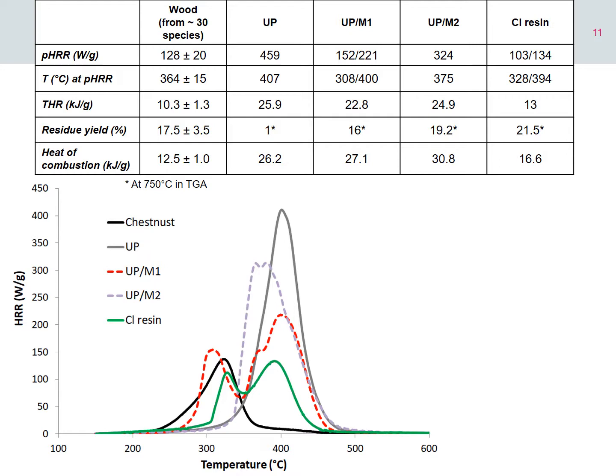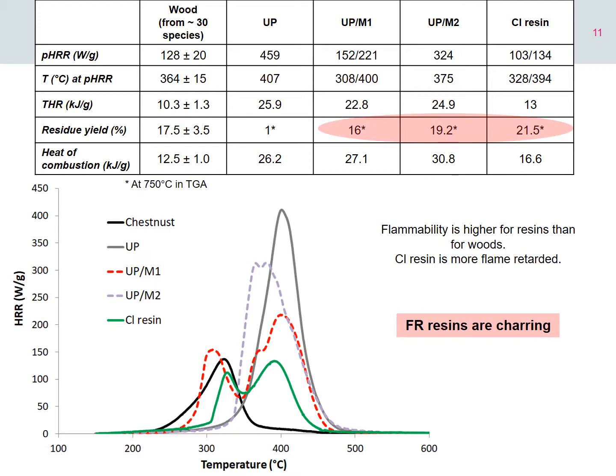From a flammability point of view, here I present some heat release rate curves at microscale using pyrolysis combustion flow calorimeter. The main drawback of our method is that our resins are more flammable than wood. This is the case of the unsaturated polyester one, but also of the flame retarded resins, including the chlorine resin, which is the best one. But at least the flame retarded resins are able to char, and the char content ranges between 16 to 21%. It means approximately the same value as wood.